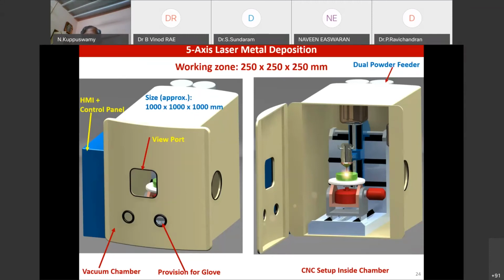Therefore, what happens is the powder is getting reused, right? You cannot throw away a powder for which you have paid 20,000 rupees a kilo. Therefore, when you use it, the powder that you're using, you think is fresh, but it's got oxygen already built into it. Therefore, you are no longer able to vouch or control that you have got a 0.28% oxygen maximum in the part. Okay, that is why a lot of people prefer RCAM, which is the E-beam machine.